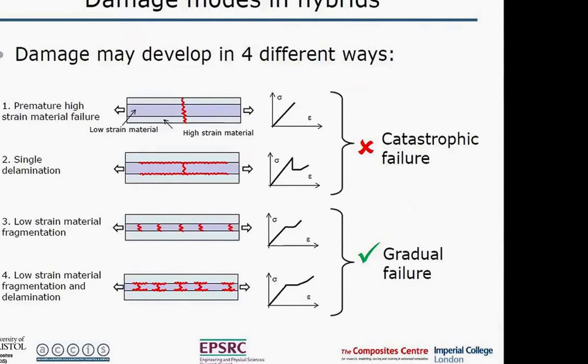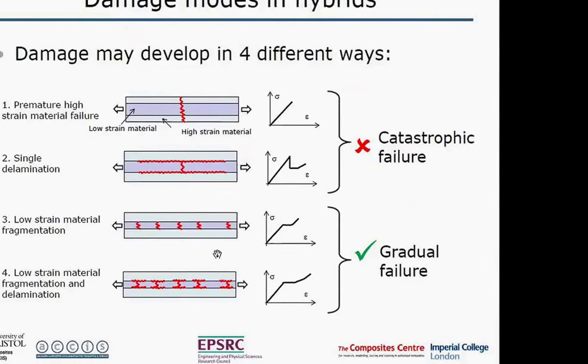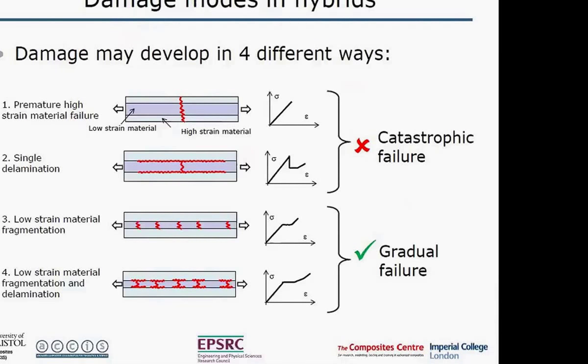So hybrid composites can fail in different ways depending on their configurations. Let's assume this is a carbon-glass hybrid, so we've got carbon in the middle and glass on the outside. If we have too much carbon, then when you load it, as soon as the carbon breaks, the whole thing fails, and you get a catastrophic failure. So you get a linear elastic response, as you would for a normal composite material, with catastrophic fiber failure.